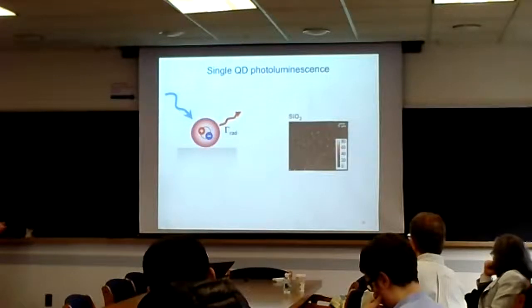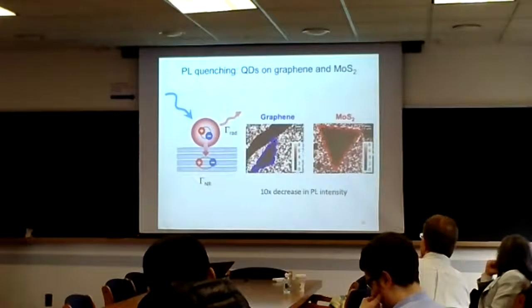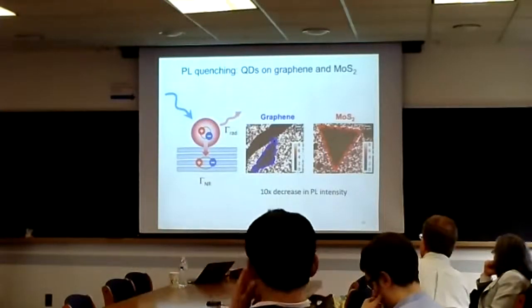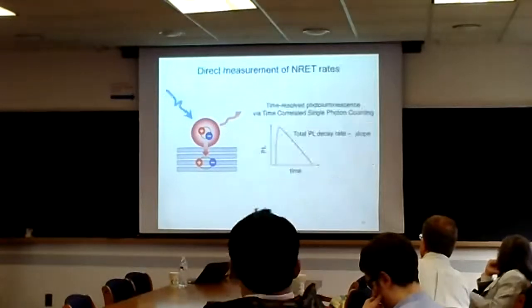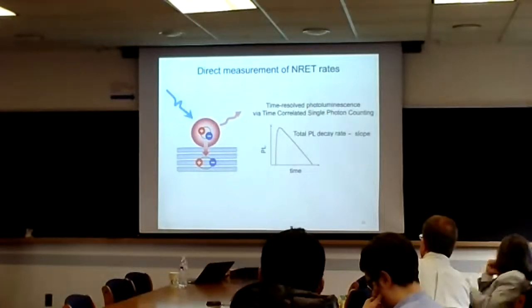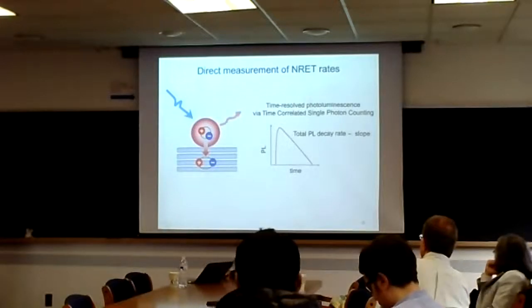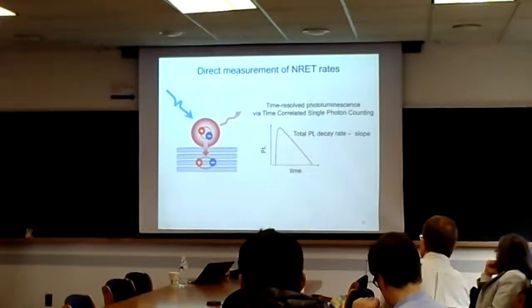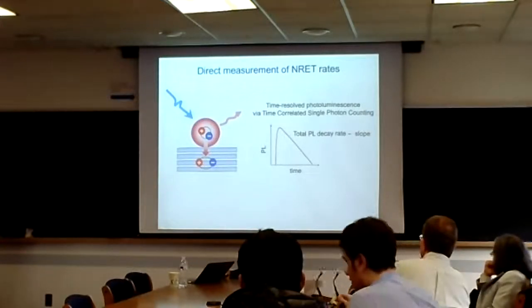Just pay attention to this scale bar here. In this photograph of the quantum dots, the main process is you come in with a laser and measure the radiative decay. Now, when you put these dots on a monolayer of graphene or MoS2, this emission really goes down by an order of magnitude. We were wondering what's going on here. The best way to measure this is through time-resolved photoluminescence. We measure the emission as a function of time, and the decay rate gives us information about the rate of the process going on.